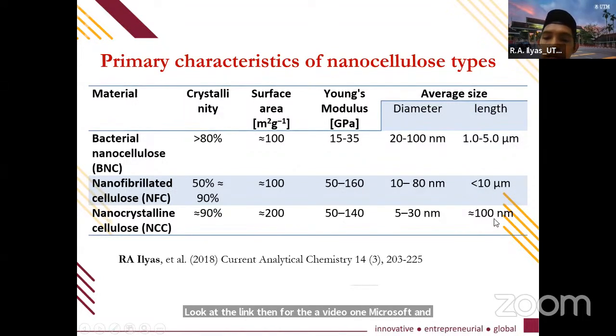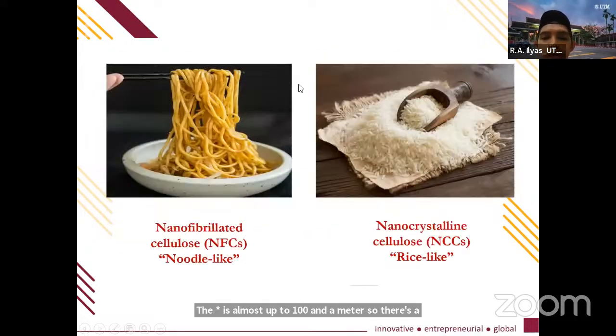However, for the nanocrystalline, the length of the fiber is almost up to 100 nanometer. So there is a difference between the nanofibrillated and nanocrystalline. You can imagine the shape of the nanofibrillated and the nanocrystalline. Crystalline looks rice-like. However, the nanofibrillated cellulose is noodle-like.